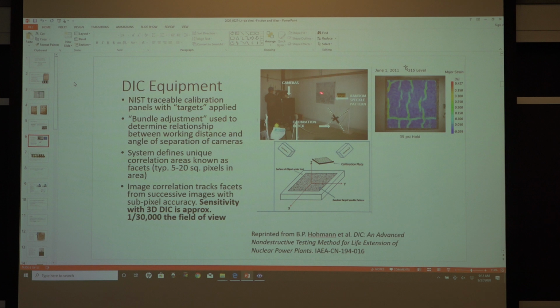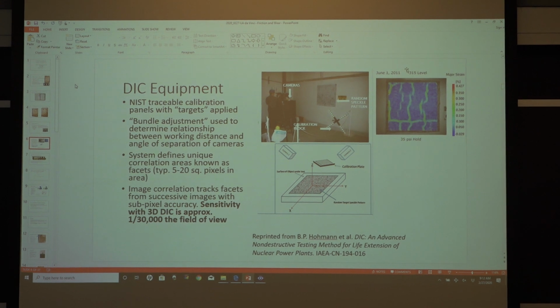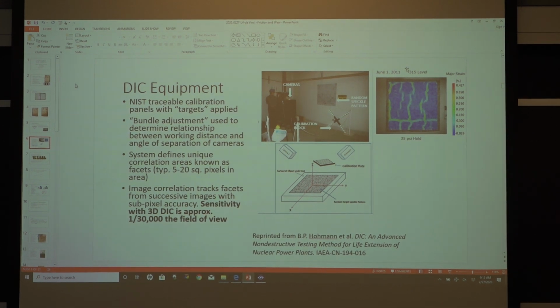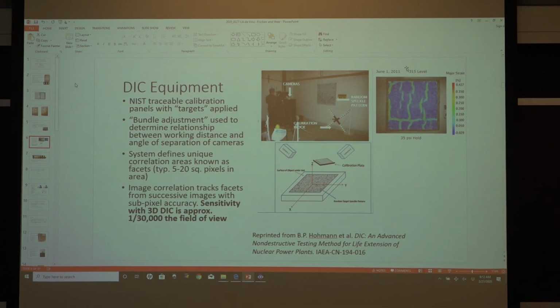What you're seeing in the image here, from the speckle pattern, is what would be referred to as a cold joint. As they're building that containment, you can only pour so much concrete every day. So when you finish one pour and go on to the next pour, you get what's known as cold joints along the vertical height in the containment. These other areas are related to stresses due to the anisotropy of concrete. This was at a 35 psi pressure. The entire containment basically goes under pressure.